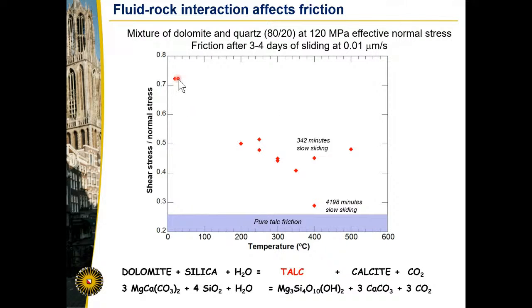And what you can see is that at room temperature, this mixture is quite strong. Dolomite and quartz are frictionally strong minerals. But as we increase temperature, we see a pronounced decrease in friction, down to a friction of about 0.3 at 400 degrees. And in fact, this low friction, or the friction at 400 degrees, depends on how long we slide. So after 3 days of sliding, we have this very low friction, whereas if we go only 5 hours, our friction is